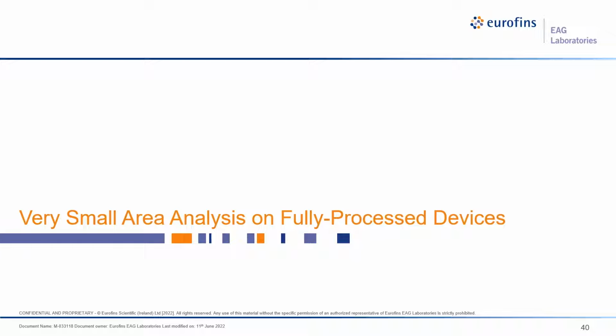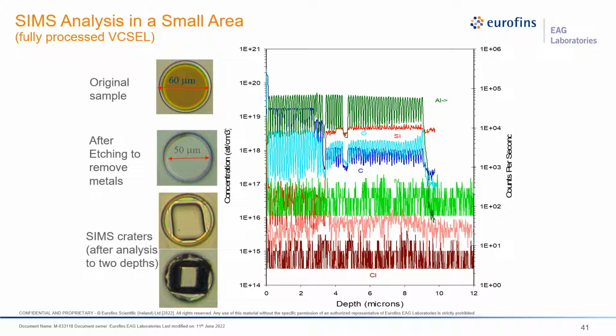However, we can do analyses not only on epi wafers, but we can do analyses on actual finished, fully processed devices. This is an example of doing a SIMS analysis on a finished VCSEL. The images to the left show the original sample, that's the top. However, there's metallization on this, and we have to remove the metallization before we do the analysis. And this requires great care in mounting the sample and polishing off the metal so the analysis can be made. The bottom two images on the left show where SIMS craters have been put into the device, and they're to two different depths. That's why they look different.